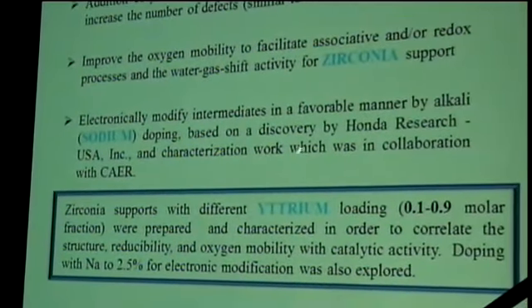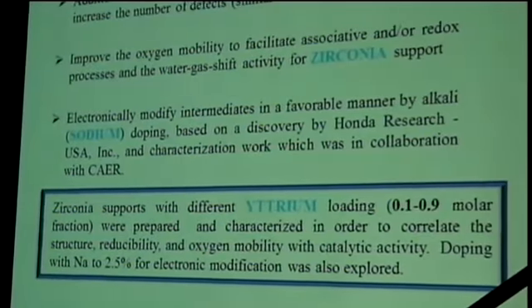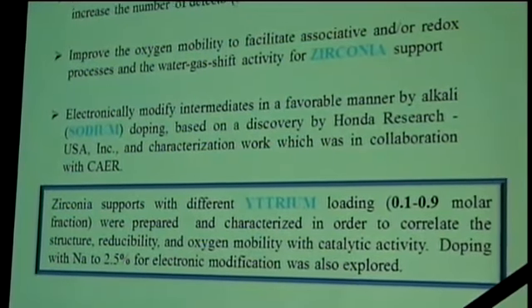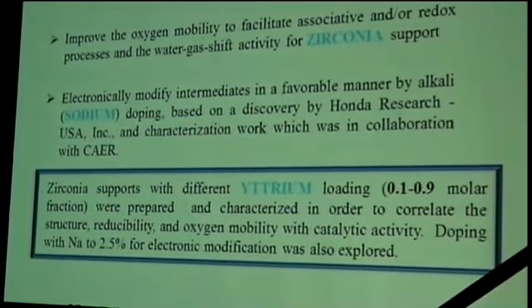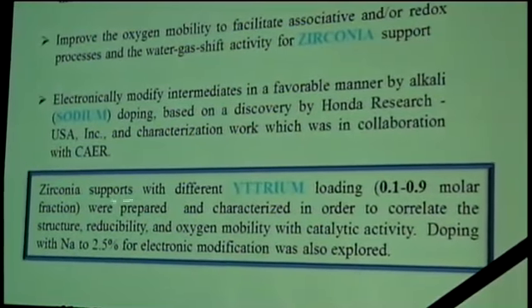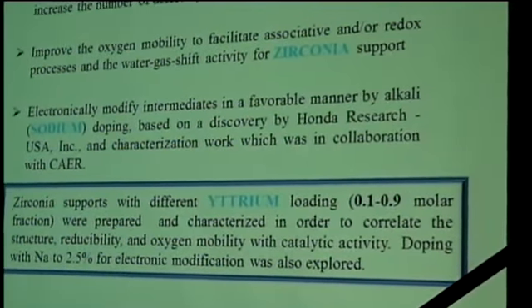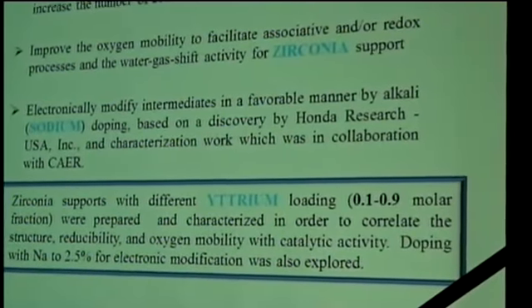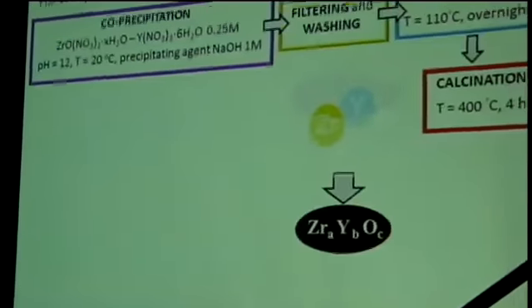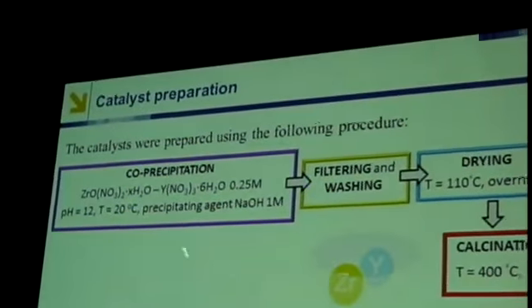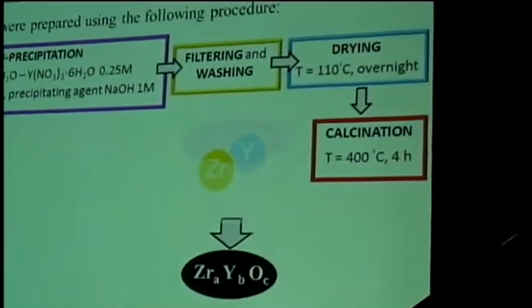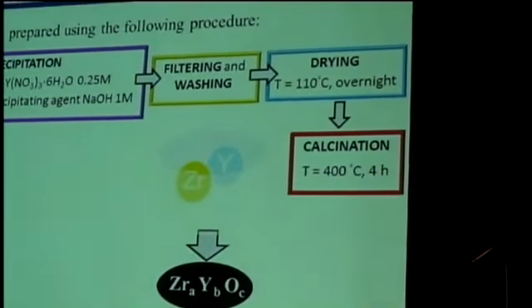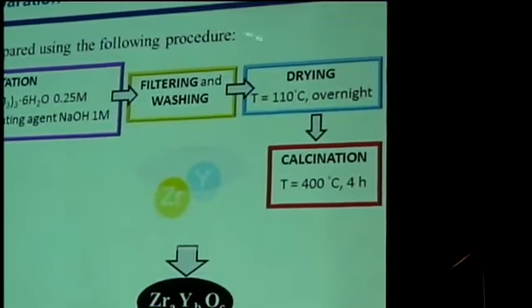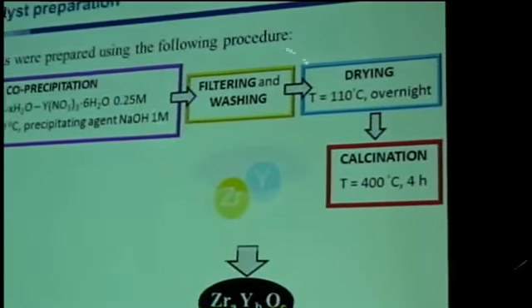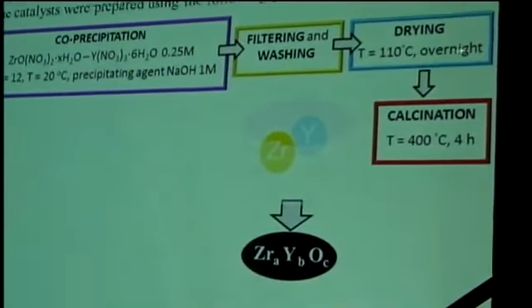And this is based on a discovery by Honda and also some characterization work that we did in collaboration with Honda several years ago. So we looked at zirconia supports doped with different yttrium loadings, and also we looked at doping sodium to 2.5%. The catalysts were prepared by co-precipitation of the respective nitrates, zirconium nitrate and yttrium nitrate. And then we collected the solids by filtering, washing, and then drying and calcining.